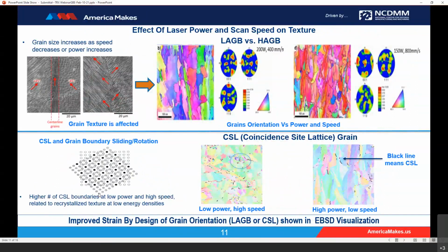Thank you. Effective laser power and scan speed on texture. It's noted that grain size increases as speed decreases and power increases. Employing our visualization technique, we're able to change power and speed settings related to a virtual build and see the corresponding changes to the grain boundaries and textures as related to the low-angle grain boundaries and high-angle grain boundaries. If you look at the image on the left, you can clearly see that the changes in power and speed have an obvious and clear effect. The grains are all aligned in a particular direction. Our EBSD visualization tool allows us to do the same thing virtually.